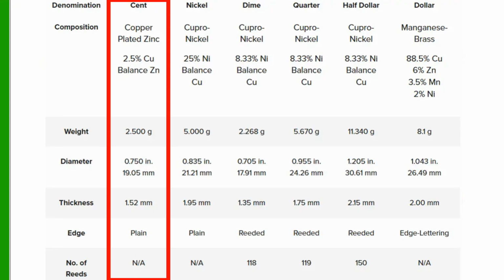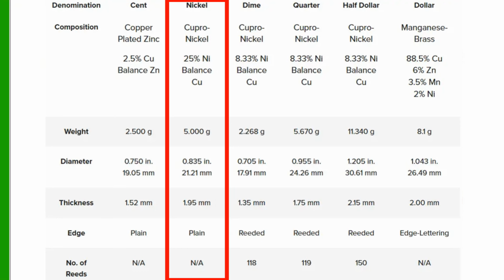For instance, the penny, as seen here, or the cent, is composed of a copper-plated zinc core, with copper making up 2.5% of its weight and the zinc comprising the balance. It weighs 2.5 grams and has a diameter of 19.05 millimeters with a thickness of 1.52 millimeters. The edge of the penny is plain. Now, when I say it's plain, it's not lettered or reeded, as you'll see in some of the other coins. The nickel is made of a copper-nickel alloy, consisting of 25% nickel and 75% copper. It weighs 5 grams and has a diameter of 21.21 millimeters with a thickness of 1.95 millimeters. Similar to the penny, this one also features a plain edge.